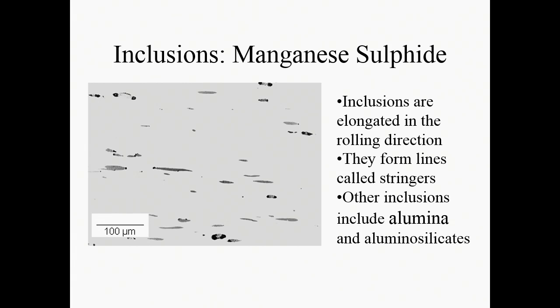Alumina silicates, again, blast furnace linings, and the insulators that are used in the steelmaking process. So you can get them throughout the steel. They've been managed. The sulfur on its own would be bad, but if you put manganese in and get manganese sulfide, that makes the sulfur's effect smaller. It doesn't remove it completely, but you're managing the impurity in that system. And that's what you do.